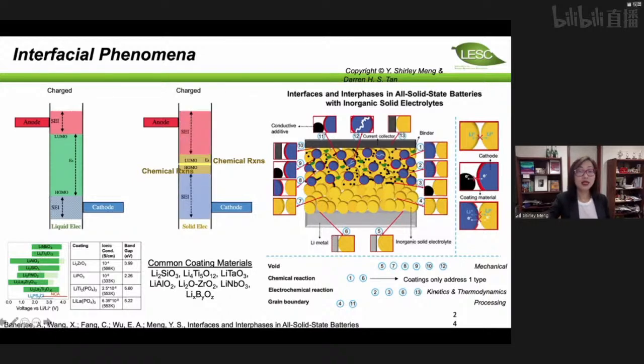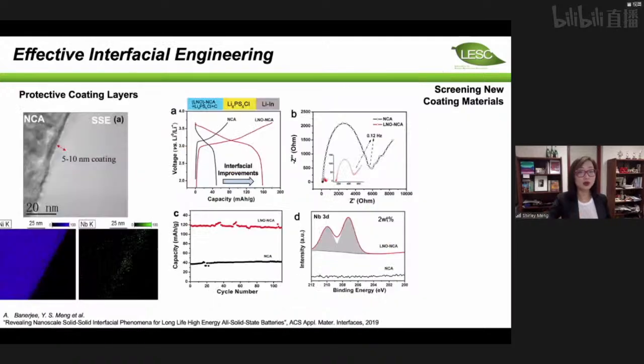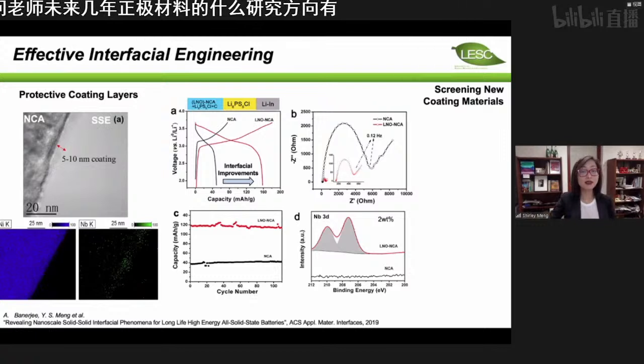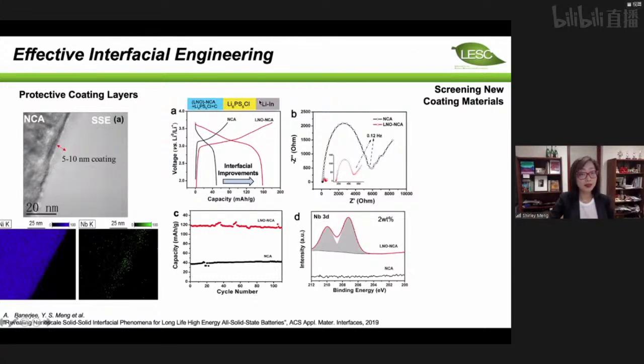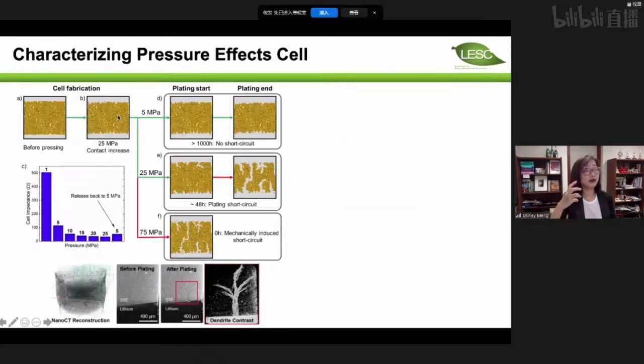Okay, so in terms of coating, I want to say that for a 5 to 10 nanometer conformal coating, material scientists have many ways to achieve that. And indeed, with the sulfide-based electrolyte and the nickel-based cathode, if you do not engineer the interface, you cannot utilize the cathode very well, and you cannot cycle the cell very well. This particular coating here is a lithium niobate oxide, which was released by Toyota many years ago, and they already have patents, right? But the problem is they do not have the same mechanical property.